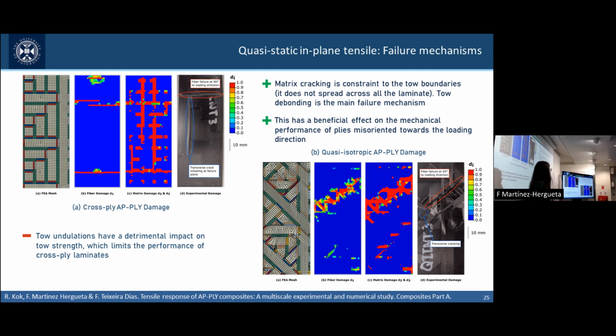And that gives us some hope that this might behave better on impact and might present a better damage tolerant response. That's the hypothesis that we've got for the improved response of the quasi-isotropic laminate. It also develops cracks, but since they are arrested within the tow boundaries instead of spread all around the laminate, they result in a linear elastic response.